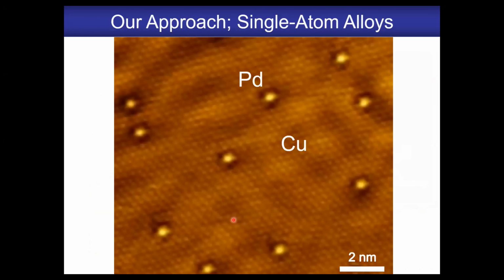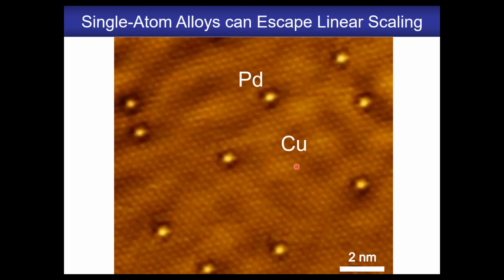Because we work in ultra high vacuum, we have scanning tunneling microscopy. We can examine surfaces with atomic scale resolution. And what we've been doing for the last 12 years is to take a less reactive host metal, like a copper 1-1-1 surface you see atomically resolved here, and then put tiny amounts of palladium, for example, more catalytically active elements, into it, where basically one copper atom pops out and a palladium atom takes its place. And that's what we term a single atom alloy. It's an alloy at the atomic scale where you have just single atoms of another more reactive element replacing some atoms of the host metal surface. And today I'll try to convince you that these single atom alloys generally can escape these linear scaling relationships.